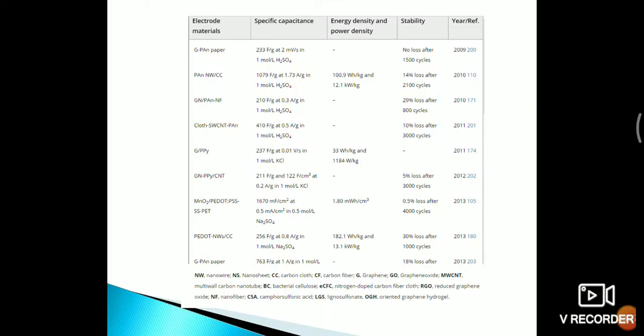Here is a comparison of various electrode materials and their specific capacitance and their energy density, power density, and their stability. As we can observe, the highest specific capacitance is shown by MnO2 PEDOT composite, that is metal oxide and polythiophene derivative composite, that showed 1670 millifarad per centimeter square specific capacitance. And it has shown a cycle stability of 0.5 percentage loss after 4000 cycles. And energy density 1.80 milliwatt hour per centimeter cube. And also the graphene polyaniline paper electrode material show no loss after 1500 cycles, that is it has a high cycle stability.